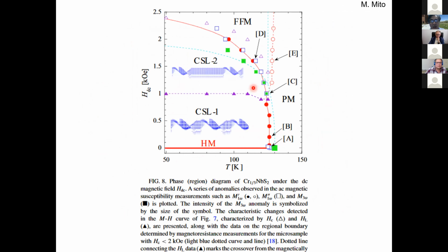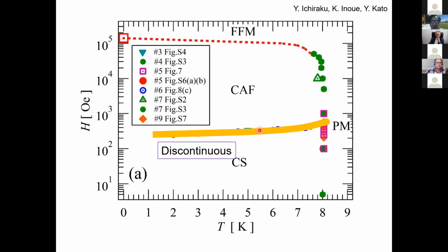Let's remember, this is the phase diagram of chromium niobium sulfur. This phase borderline is upward convex. This is completely opposite. And here are many solitons, reducing the number of solitons, and reducing, and going to one soliton, and here is zero solitons. The soliton number is changing 0, 1, 2, 3, like this. Then this line is a continuous transition. The difference is 1 and 0. It's completely different. But our case is a discontinuous transition. Here is a phase transition, not soliton 0, 1 like a continuous transition.